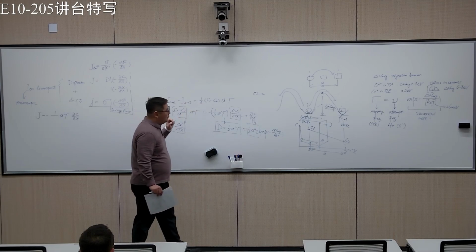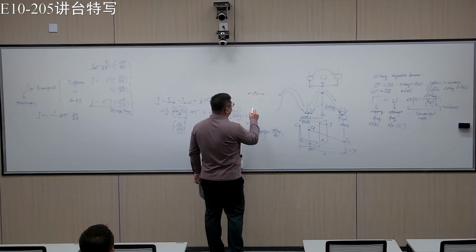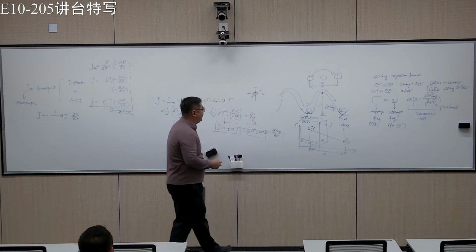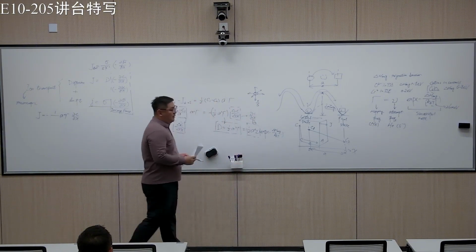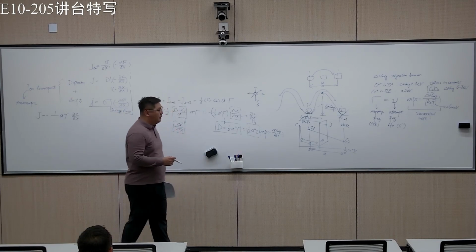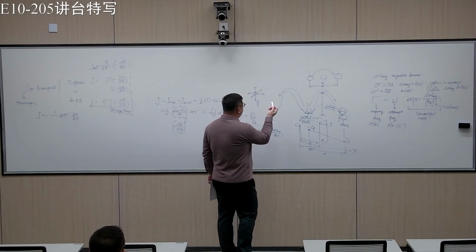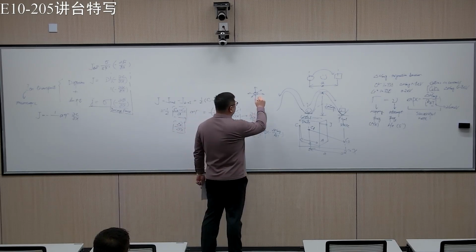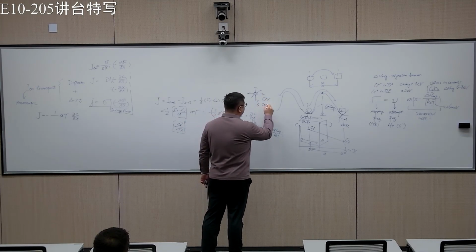But imagine if you are in three dimensions, the ions can hop this way, or that way, or this way, so you can have 6 probabilities. In real ionic crystals, things are more complicated because you have specific ionic structures that have something to do with the coordination number.